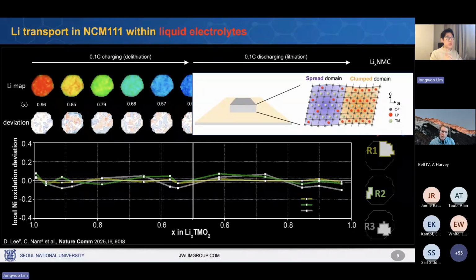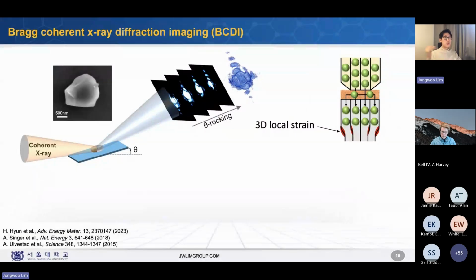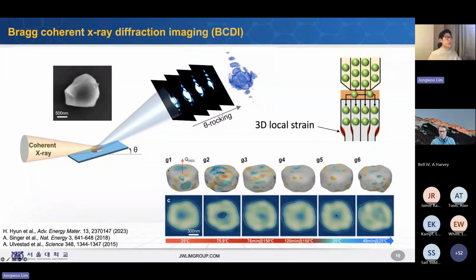So what we developed is Bragg coherent X-ray diffraction imaging. So we use coherent X-rays to get the diffraction pattern. And if you get the diffraction pattern, there are many features in there. If you reconstruct those features, now what we can do is get three-dimensional strain information in situ. So based on the diffraction pattern, which has all the strain information, we take the inverse Fourier transform and get the reconstruction, and you can get a 3D strain map. This is one of the recent papers we published about 2 years ago.